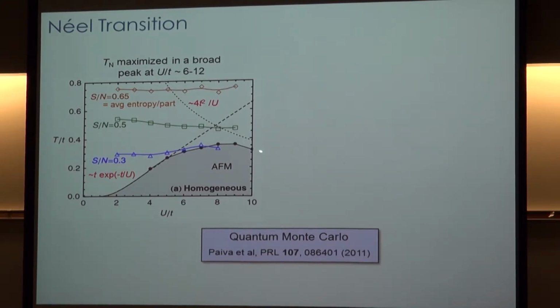So this is the superexchange energy scale. At very low interaction strengths, the superexchange energy scale crosses over to a different scale, which is exponentially dependent on t over U. And so there's a sweet spot in interaction, which ranges from about 8 to 10 in these units. If you get in there, presumably you maximize the Néel temperature. And relative to the hopping, the Néel temperature is about 0.4 of the hopping energy.